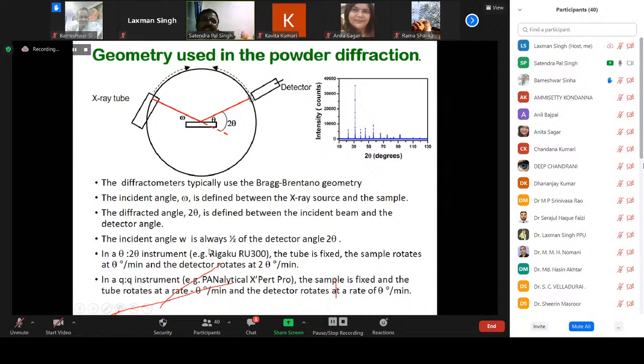So depending upon these conditions, there are various instruments which measure the powder patterns, which look like this. In a theta-2 theta instrument, that is Rigaku, the tube is fixed and the sample rotates at theta degree, and the detector rotates at 2 theta degree per minute. In a theta-theta instrument, like PANalytical X'Pert Pro, the sample is fixed and the tube rotates at theta degree per minute, and the detector rotates at theta degree per minute. So depending upon the geometry, one can design whether to fix the X-ray source and rotate the sample, or move the X-ray source and fix the sample. All the instruments, based upon their requirement, are designed appropriately.